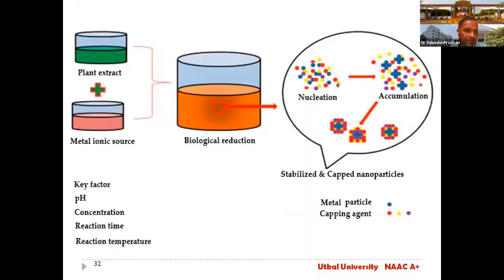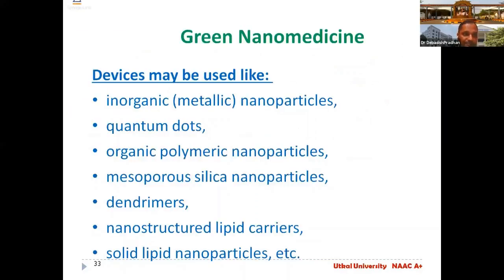You see this one again, the plant extract with the metallic ion source, then the biological reduction happens over there with the nucleation and accumulation, then they get stabilized and capped nanoparticles, with the metal particle capping agent over there. Then we will have to go through some key factors like pH, concentrations, reaction time, reaction temperature, and we'll have to evaluate thereafter. So these green nanomedicine devices may be used, like inorganic metallic nanoparticles, quantum dots, organic polymeric nanoparticles, mesoporous silica nanoparticles, dendrimers, nanostructured lipid carriers, solid lipid nanoparticles, etc.